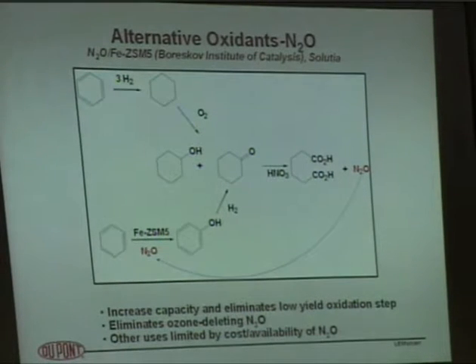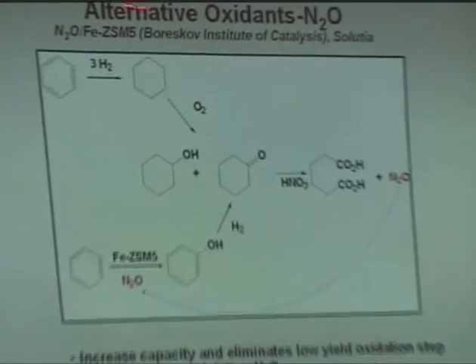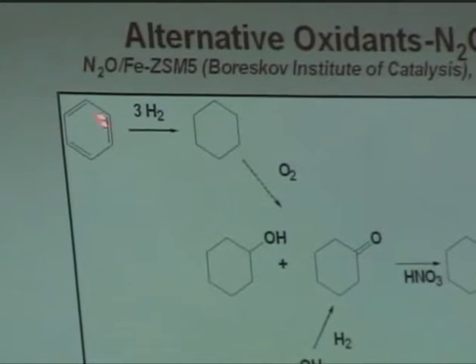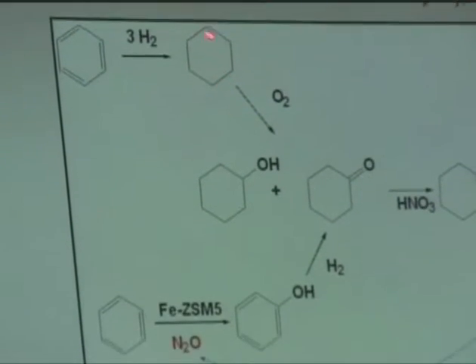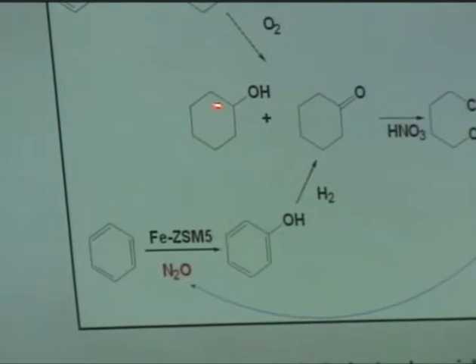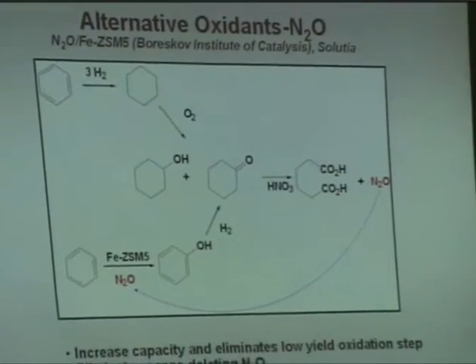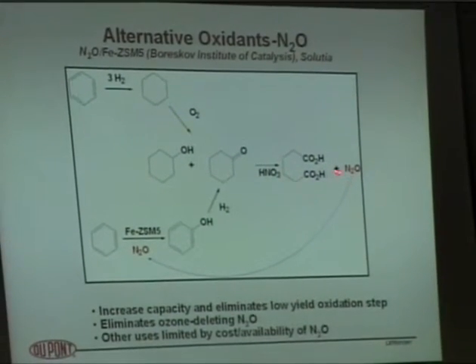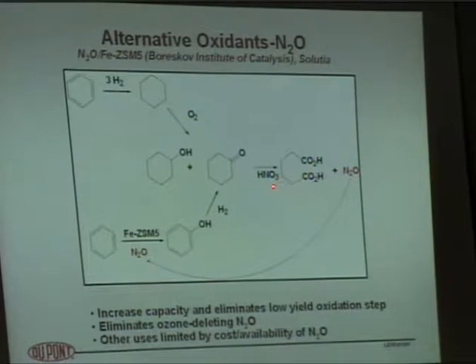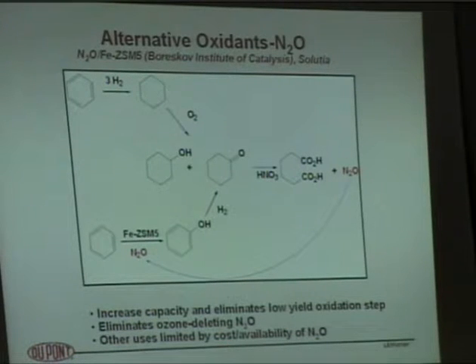Their intention is to commercialize this in an improved process to make adipic acid. Now, we at DuPont and most other people in the world take benzene, hydrogenate it to cyclohexane, oxidize it to cyclohexanol, cyclohexanone. This mixture is then oxidized with nitric acid to give adipic acid. There's a very large amount of N2O that's produced in this oxidation with nitric acid. For many years, that N2O was vented to the atmosphere, was not considered to be particularly harmful, but it then became known that it was an ozone depleting gas and a global warming gas.